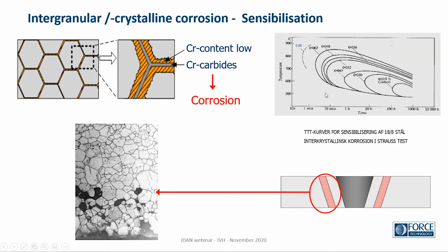Another way to do it, and especially in Germany, it's the preferred way to do it, is to add titanium or niobium, which would form carbides, and that way reduce the amount of carbon which could make chromium carbides. So either a very low carbon content in itself, or addition of something which pulls carbon out of the material into other carbides, which doesn't affect corrosion resistance. We call them stabilized grades.